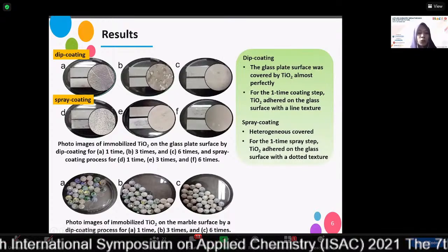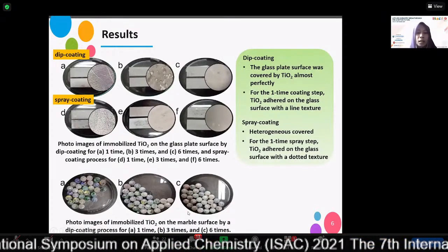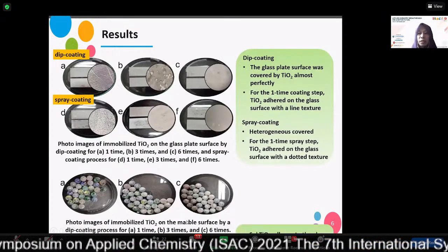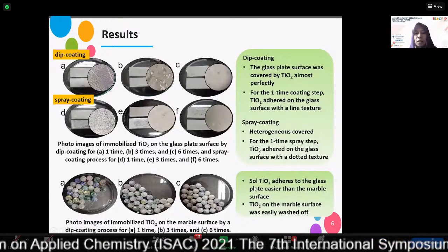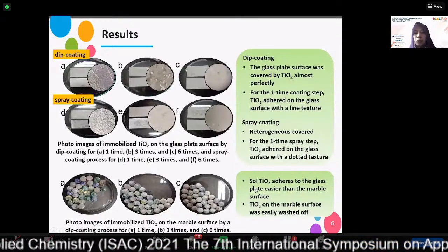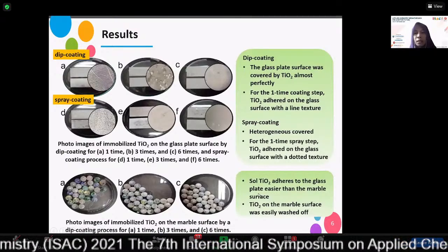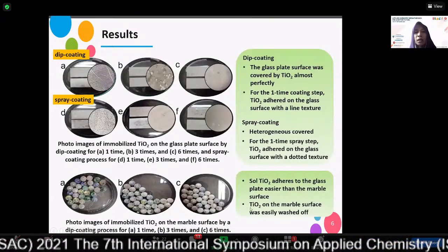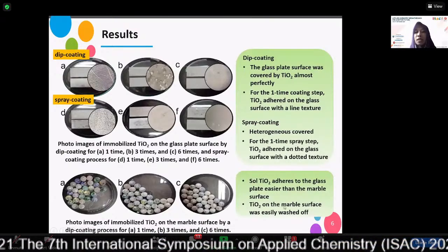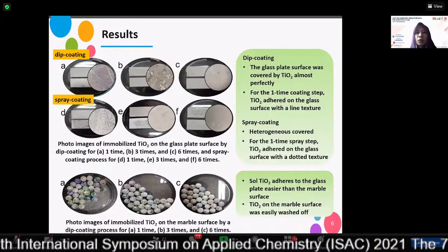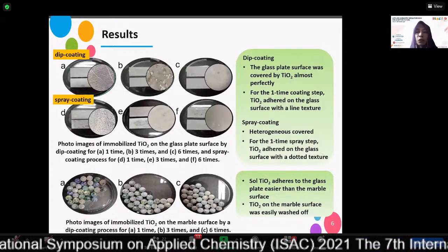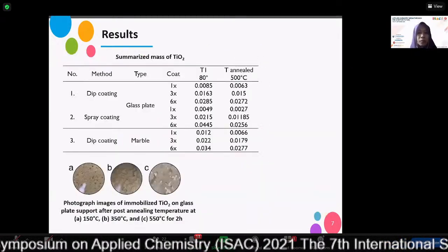And then this is for comparison, we also did it for a marble's surface. And the result is TiO2 sol adheres to the glass plate easier than the marble surface, and TiO2 on the marble surface was easily washed off. Therefore, the glass surface is better.